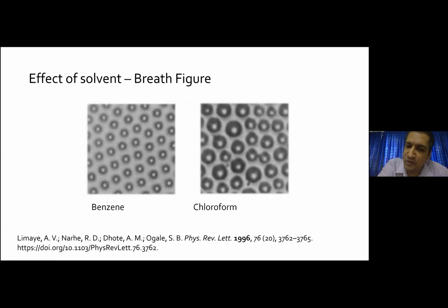Since the surface is getting cooled, if you pass humid air, the humidity tries to condense into regular hexagonal droplets. In the case of benzene, they get very small pores. In the case of chloroform, they get very large pores.